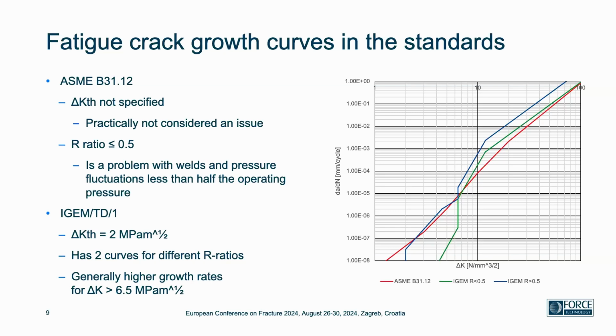The IGEM TD/1 has two curves, one curve for the R ratio less than 0.5, and the blue curve for an R ratio higher than 0.5. This standard has a threshold defined at 2 megapascal square root meters, and it has two curves, as mentioned before. In general, the crack growth rates are higher in the IGEM compared to the ASME code, at least for the delta K above 6.5 megapascal square root meters.